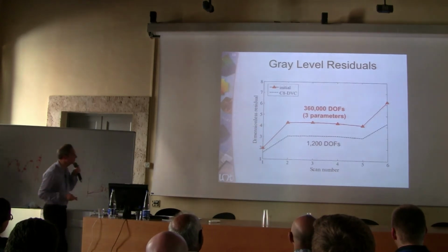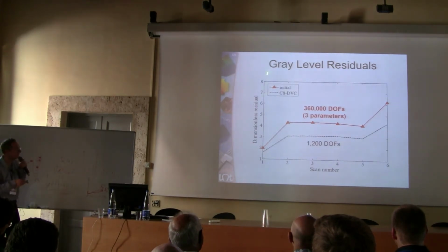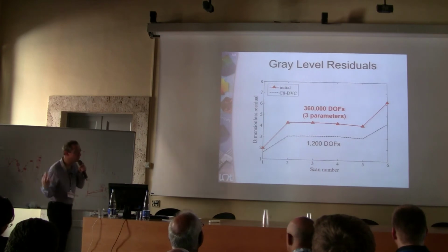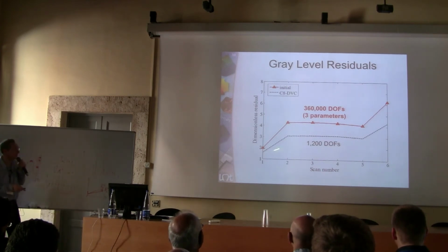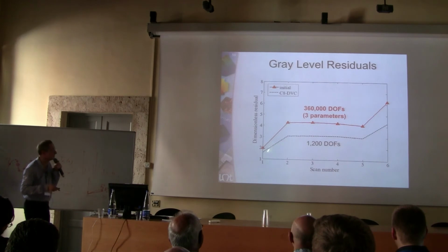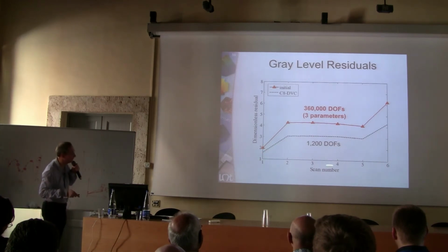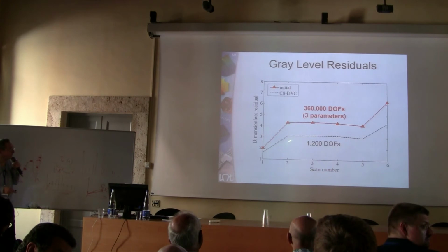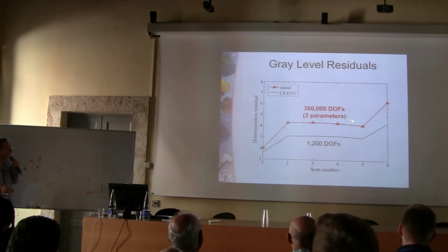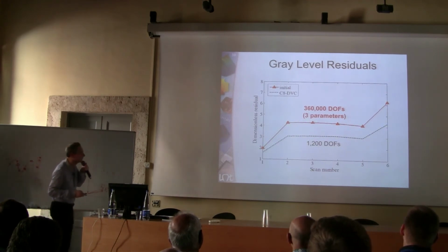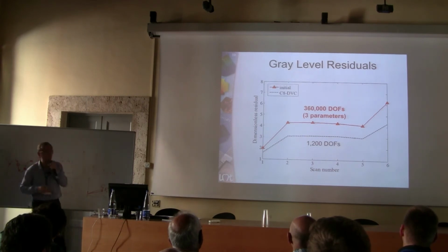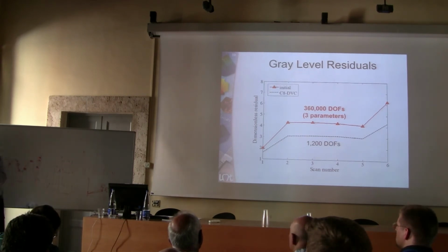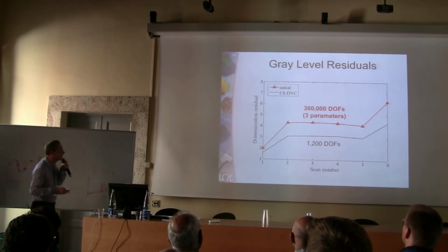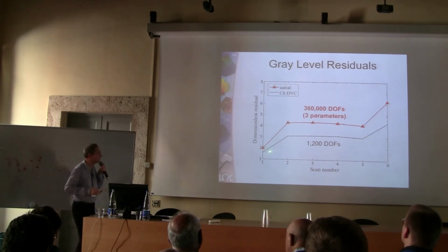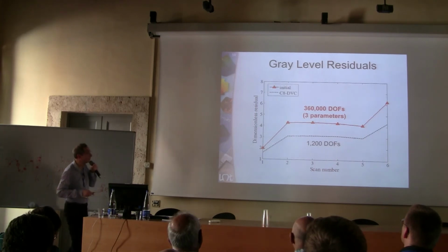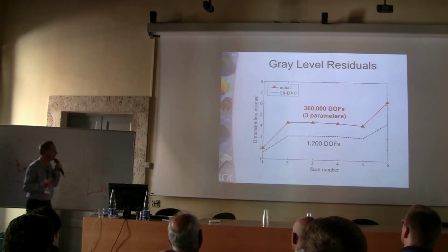And so in this particular case, now you have the gray level residuals normalized by the baseline level, which is here 1, which tells you that something is going on as a function of the scan number. And here you see the pure DVC result, and on top of it, the numerical simulations. So even though the mesh was something like 30 times finer than the experimental one, it's still performing poorly in comparison with standard experimental information.